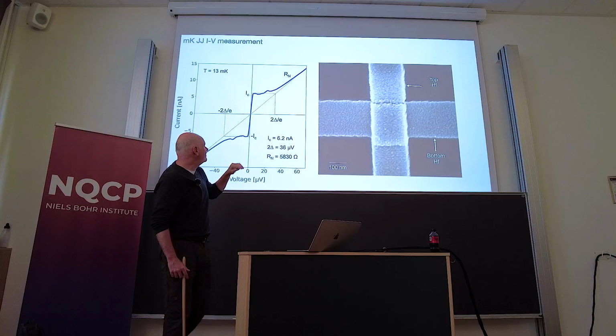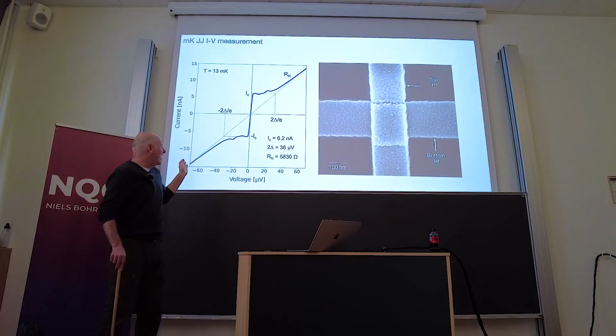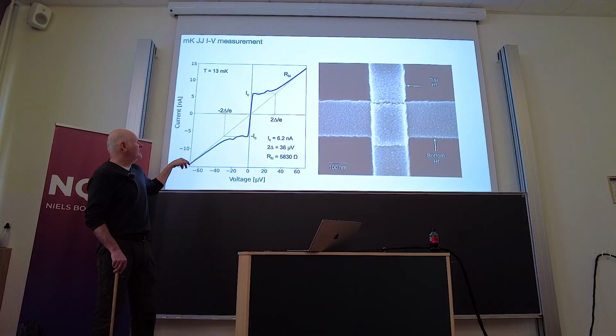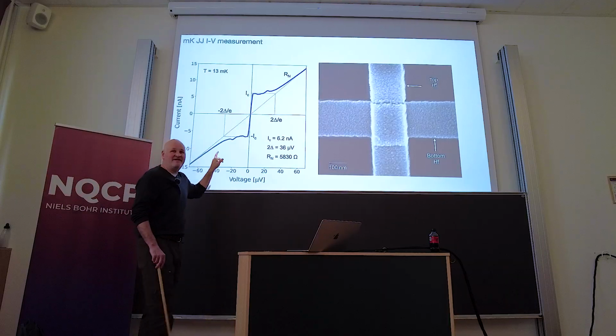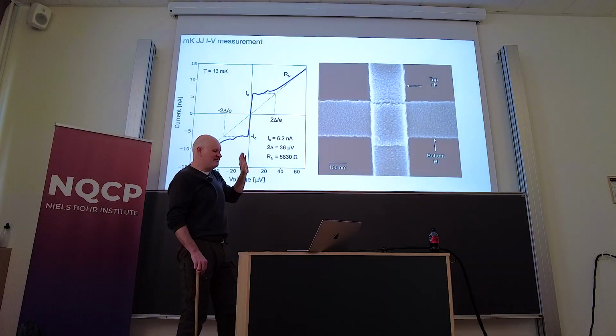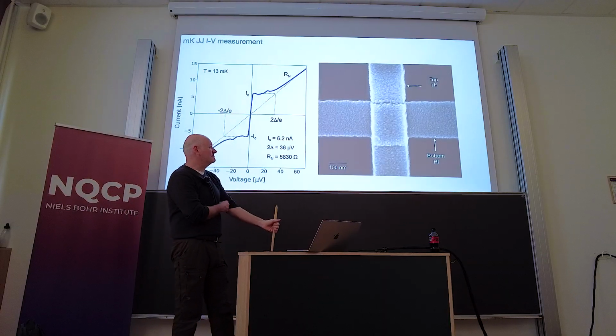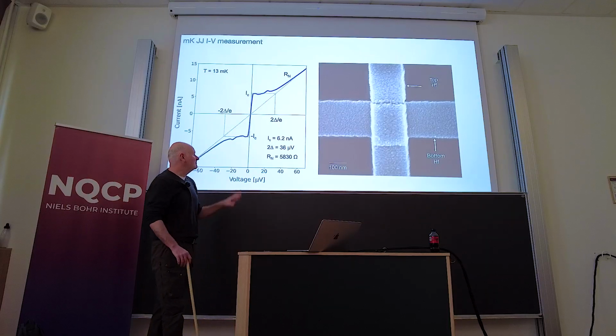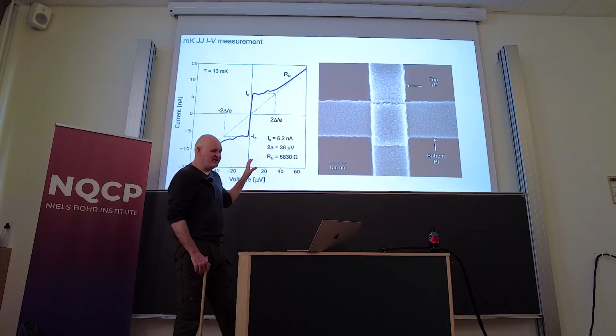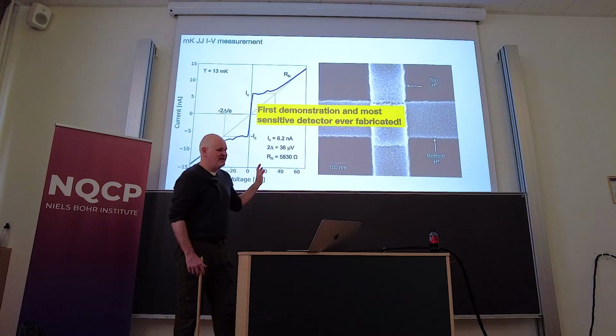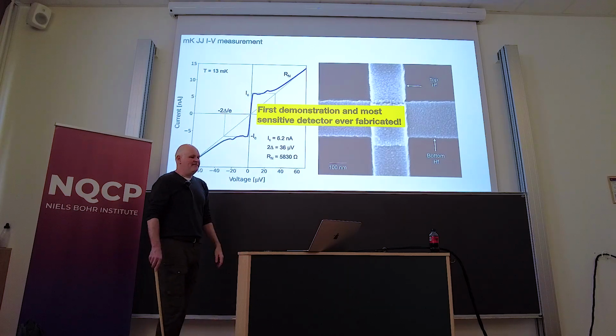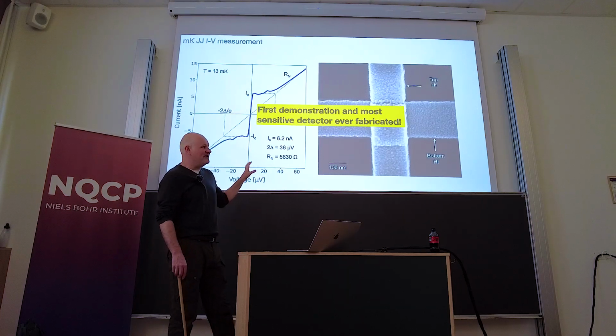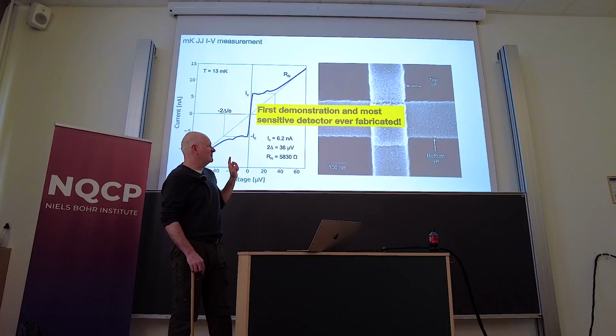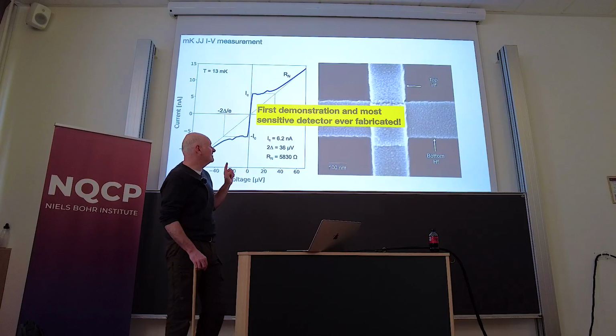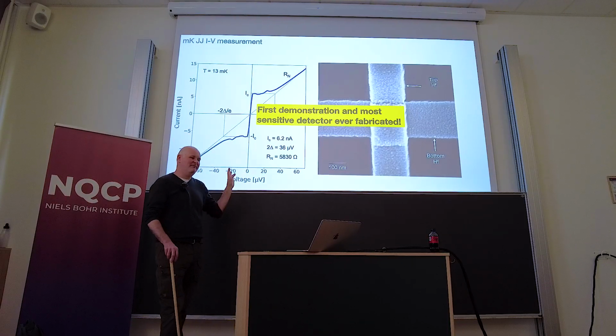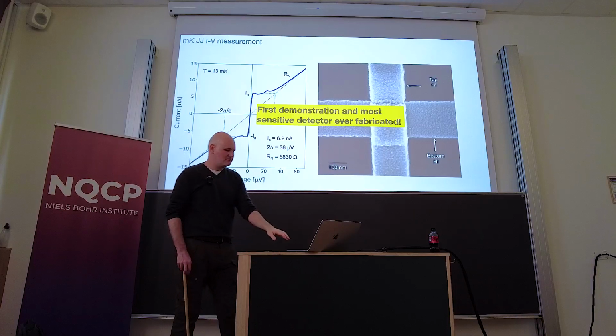We then cooled it down and did IV measurements, and sure enough, we see a transition. There's a lot of physics in this that, to be honest, I don't fully understand as well as my postdoc Yash does. But essentially, it is a JJ. It's a functioning JJ, and it is the first demonstrated hafnium JJ, and will soon be the most sensitive detector ever fabricated once we make a device out of it.